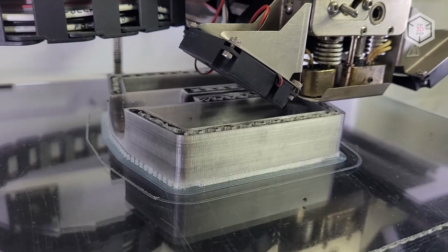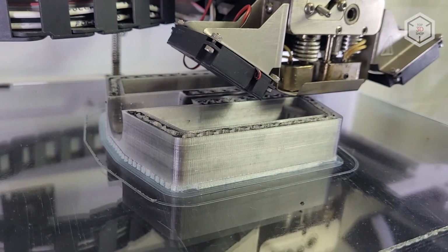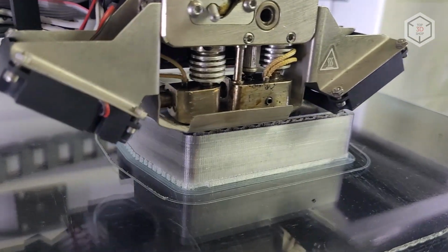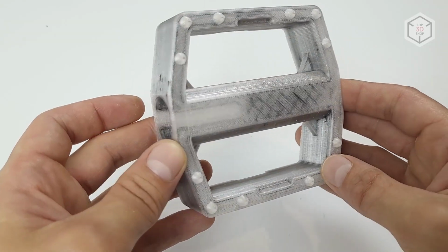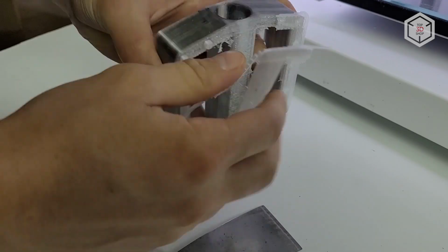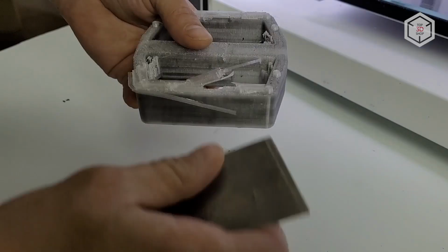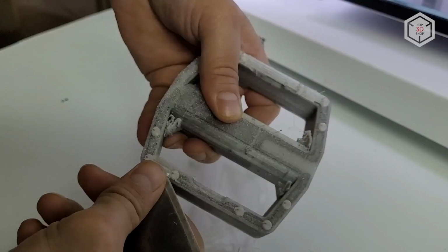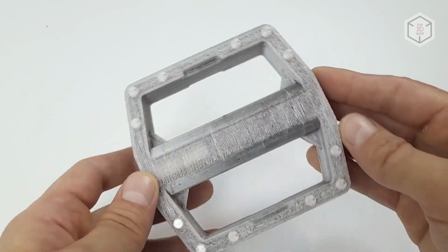Another thing we printed in the course of testing was a bicycle pedal. It allowed us to combine both the reinforced contours and the infill. Again, though, there were some areas with none of it. With this model, we checked the Cura Slicer's ability to build support structures, and they were built well and easily removed without leaving any marks on the surface.